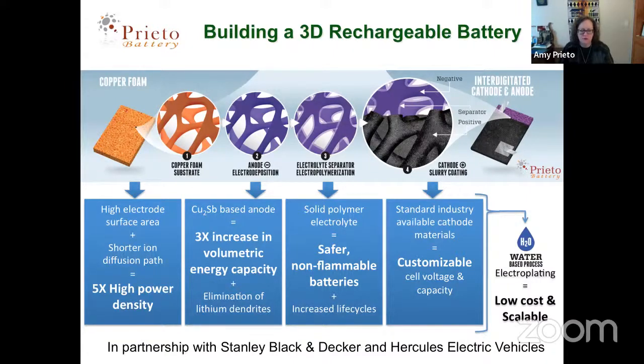But if that's the working electrode, we can then use it for step 3 to electrochemically polymerize or electrochemically coat a polymer electrolyte. We chose polymers because they are mechanically flexible and they can be designed to have very high breakdown voltages, which leads to safety in the battery. We then spray coat or print cathode slurries directly onto that polymer. So the polymer is our electrolyte and it is also our separator. And then for the cathodes, we just use standard industry available cathode materials with binders and additives that can be dried, and then aluminum mesh is the current collector on that side.